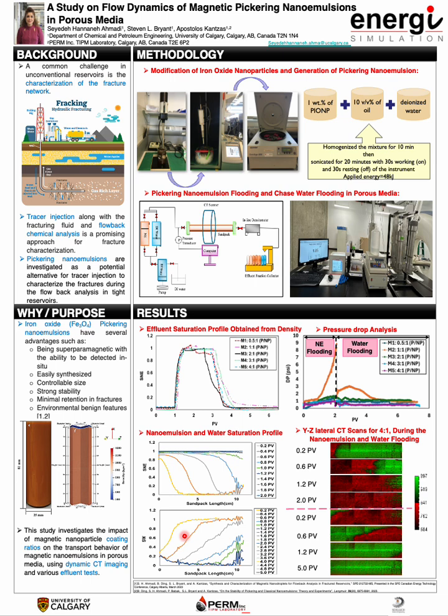The nanoemulsion flooding process continued up to 2 pore volumes, followed by 5 pore volumes of water injection to displace the nanoemulsion with a less viscous liquid phase. Before the water phase breakthrough, during the water flooding, an inclined front between the two phases, water and nanoemulsion, is observed, with a greater saturation of water at the top half of the sandpack due to gravity override. In other words, the water displacement was relatively uniform at the sandpack inlet and became more channeled, bypassing the nanoemulsion further downstream. You can see these results here.